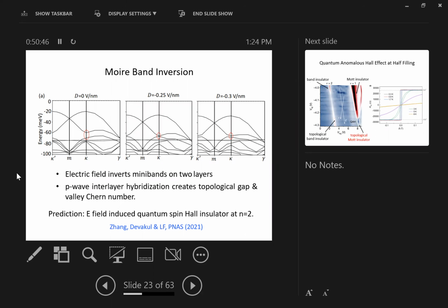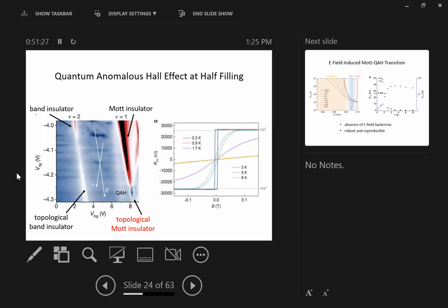Also, now this calculation is done for the two layers combined. So there's interlayer tunneling. That hybridization actually leads to a topological band inversion. It leads to a Chern number within each spin species. The two spins come from two different valleys, and they have opposite Chern number. So all this is basically a detailed example of the topological band insulator transition I showed in the beginning in the introduction slides. The consequence is that when this band is completely filled, at filling factor 2, electric field will tune the transition from a trivial band insulator into a topological band insulator, and that explains why the gap closes and reopens.